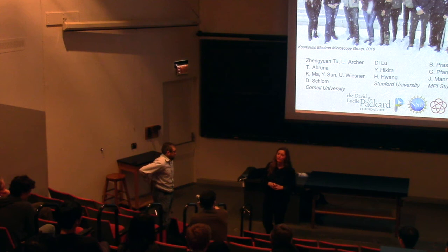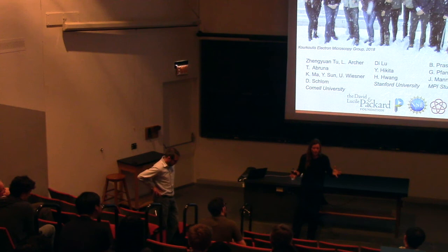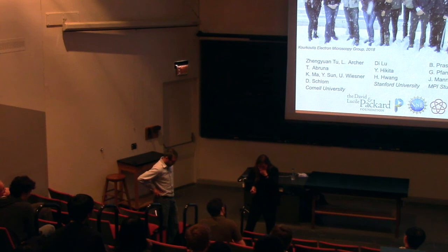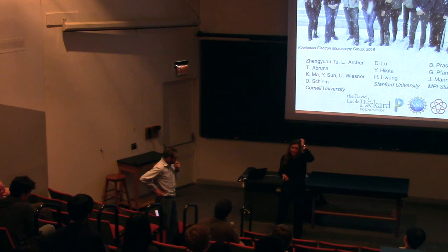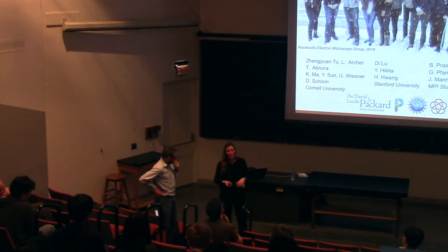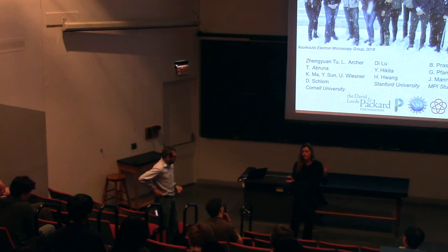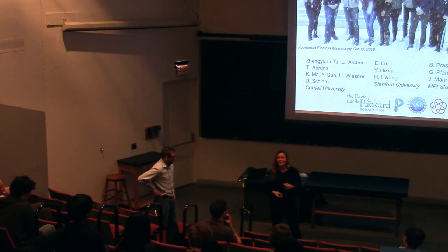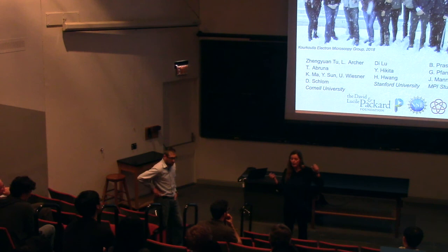and time resolution. So relatively decent spatial resolution would give you maybe picoseconds or more. But what we are doing as part of CBB, the Cornell Bright Beams, which you guys are part of, is setting up an ultrafast diffraction setup. And lots of people have demonstrated this, where you can actually look at very, very much faster time scales. So the goal would be to get to sufficiently fast time scales that you can look at structural responses. There has been work on tantalum disulfide looking at charge relaxation versus structural relaxation, looking at the Bragg spots exactly of the superlattice and the Bragg reflection.